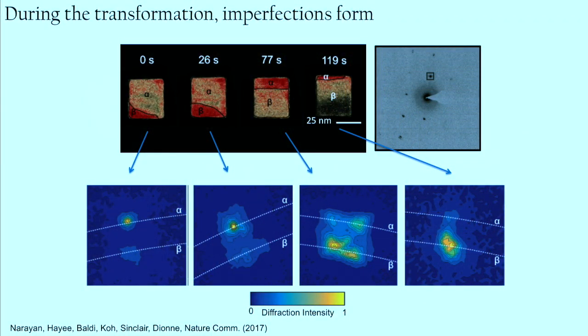And for those of you who recall your diffraction classes, as a diffraction peak full width half max is increasing, there are essentially lattice imperfections that are being formed. And that comes from the lattice mismatch between both of the phases. So even though we have two phases coexisting, there are various lattice imperfections and defects that are forming. But intriguingly, at the end of the transformation, you'll see that the full width half max of the diffraction peak has tightened up again. And in fact, when the transformation is complete, this single crystalline nanoparticle goes back to being a single crystal, and in fact, a better single crystal than how it started off.